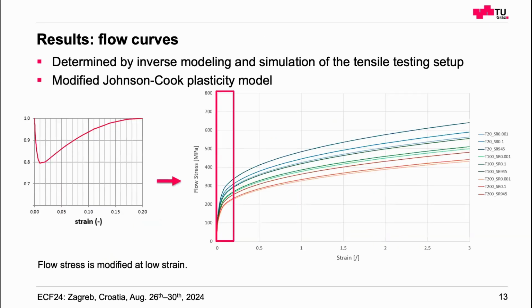Out of these real tests, we optimized our Johnson-Cook plasticity model. There we saw we had a problem at lower strains because the stresses in this Johnson-Cook model were too high, and therefore we implemented a correction factor, which you see here, and this adapts our standard Johnson-Cook model to our modified Johnson-Cook model in this region of 0 to 0.2 of strain, and lowers the stress in this region. This was very important, but I let you see this afterwards.